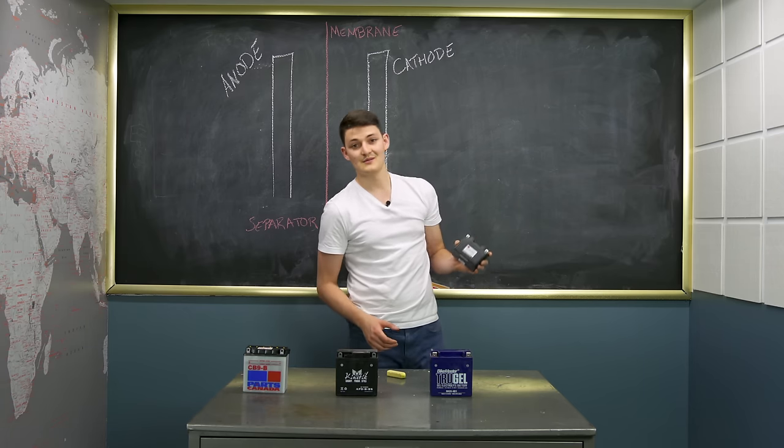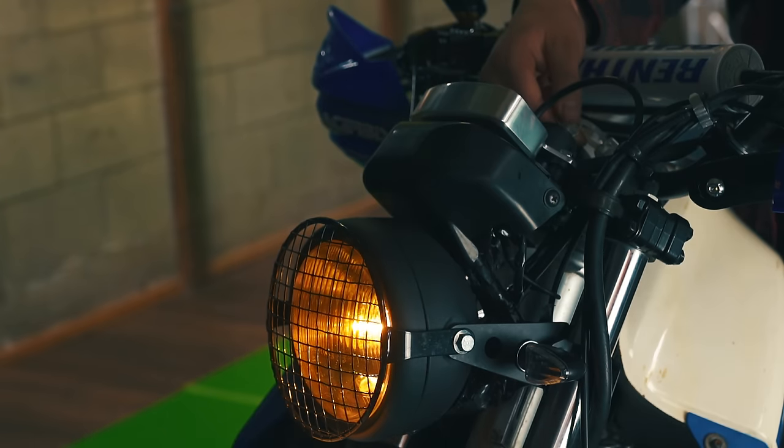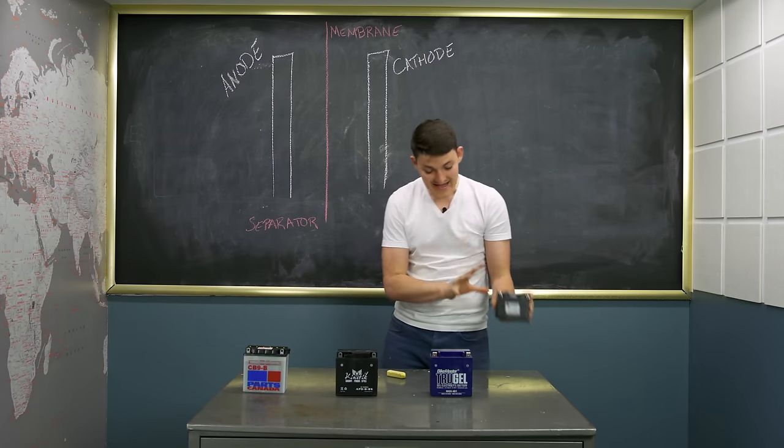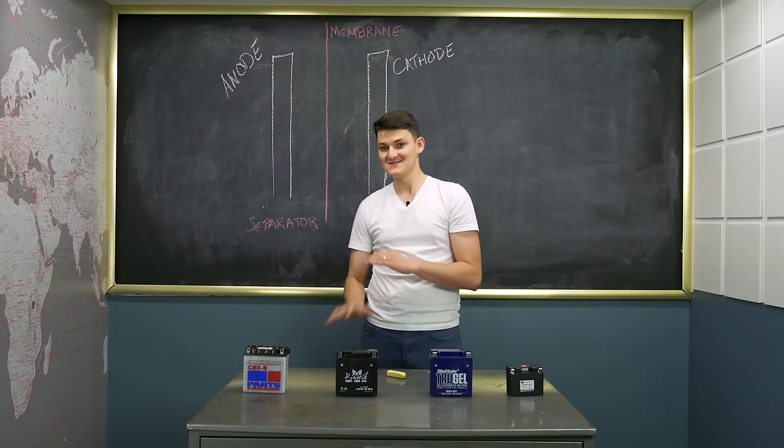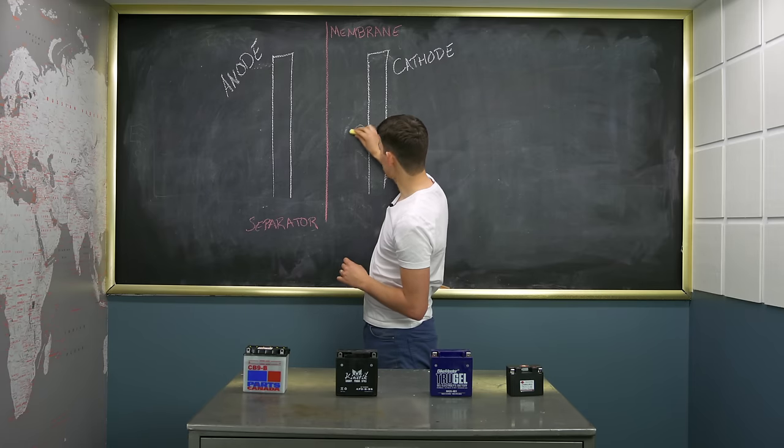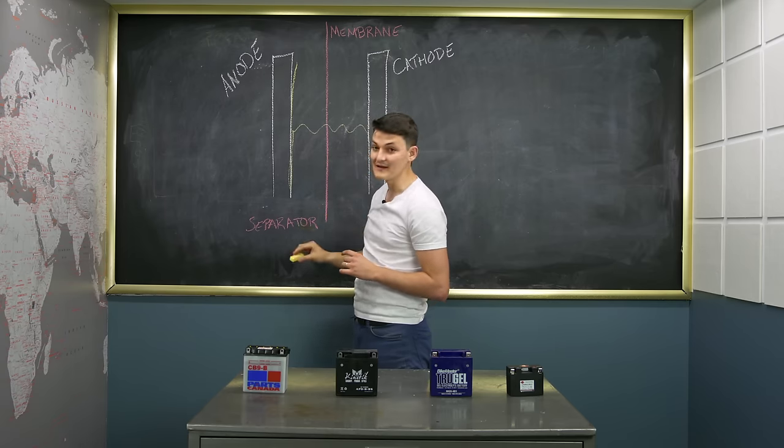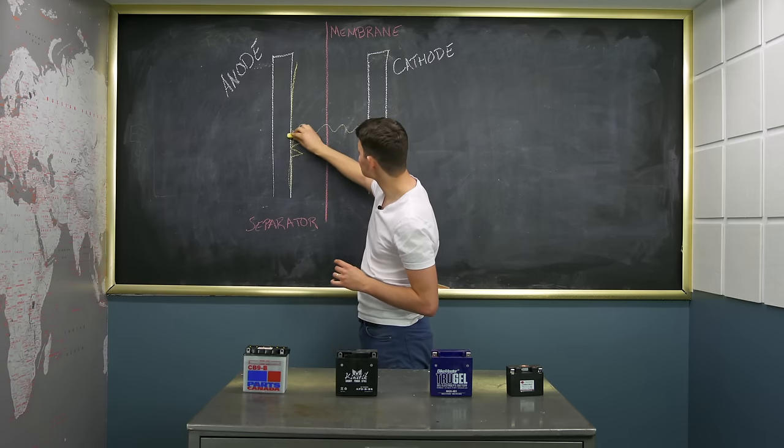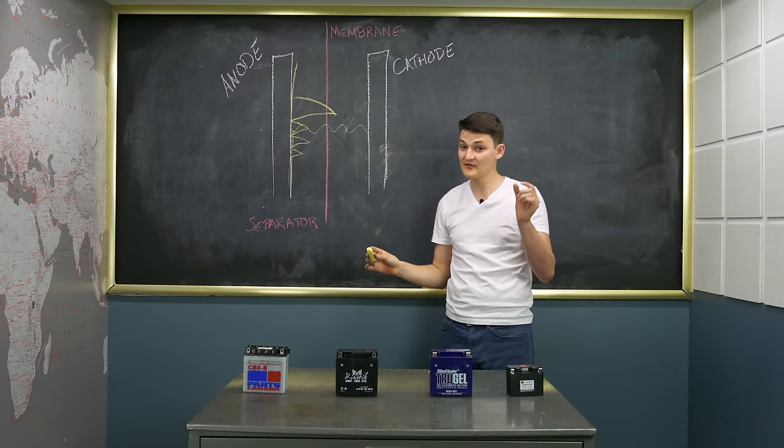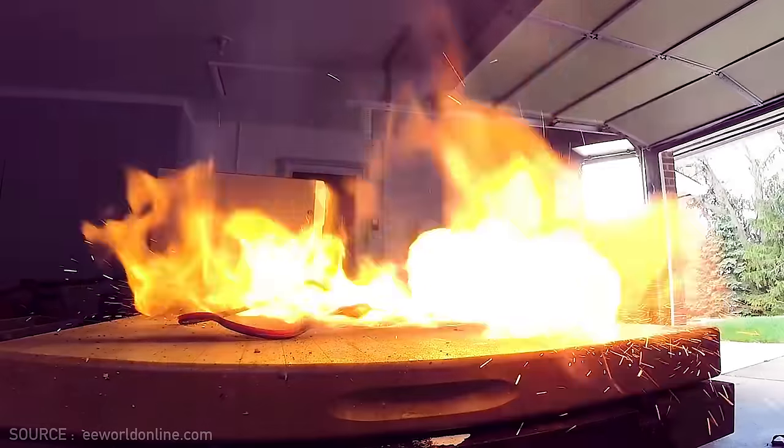But you gotta know what you're doing with cold lithium. For one, these bears hibernate in winter. You must wake them up with 30 seconds of headlight action before hitting the starter. And two, never charge a lithium battery below zero degrees Celsius. At that temperature, instead of intercalating into the anode, the ions start to plate it, forming dendrites, spiky dendrites that can pierce the membrane to the cathode and poof. Small short, big fire. Holy crap!